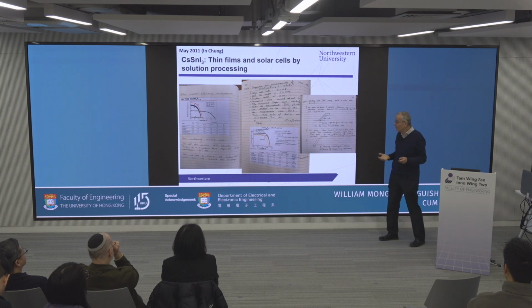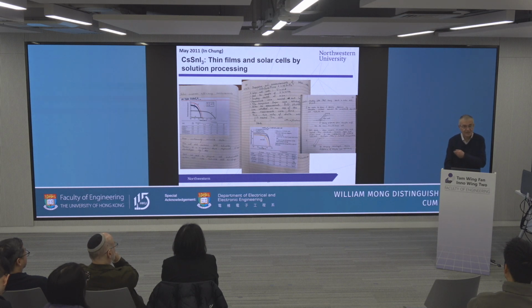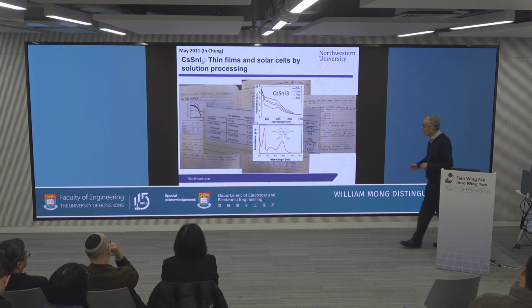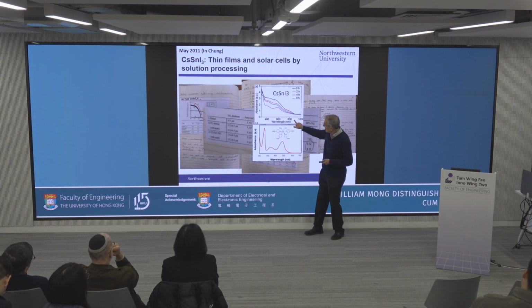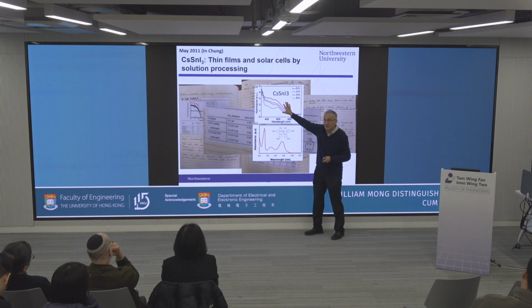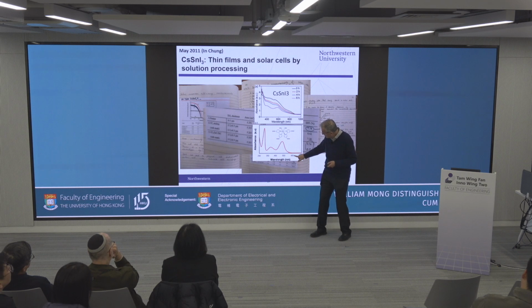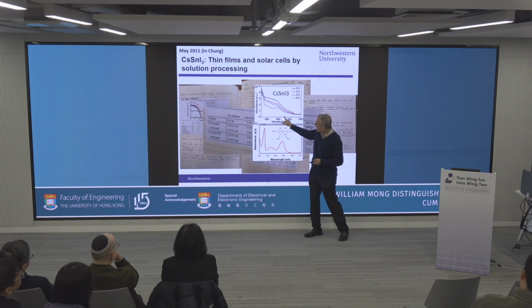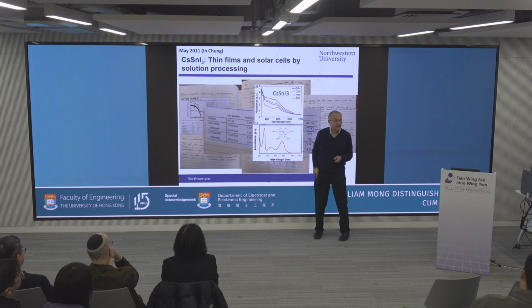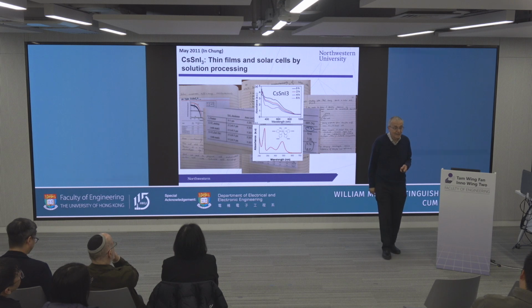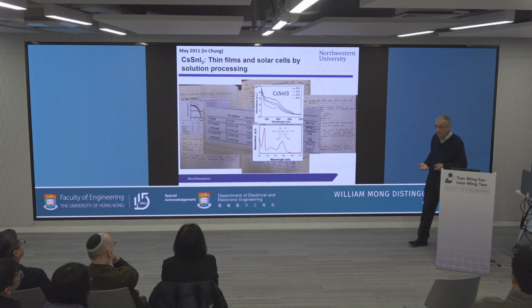The dye cannot compete for absorption because the band gap is 1.3 eV, and the dye, if you can talk about a band gap, is about 1.8, 1.7. So here's where the perovskite is absorbing already at 900 nanometers. That's the film, that's the device. The molecule is absorbing at 650. So a molecule is absorbing here, the perovskite here. The dye is not doing anything. It's the perovskite acting as an absorber and at the same time as a hole transport layer.